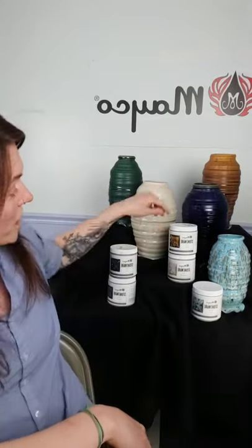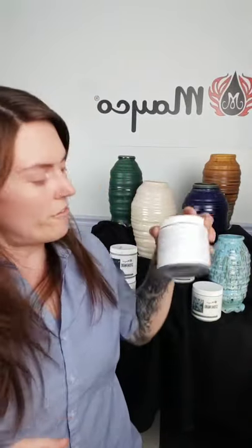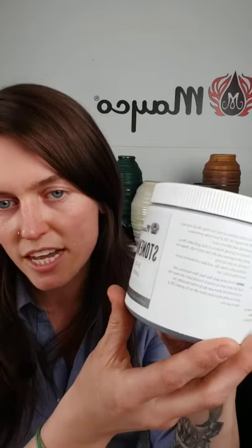Someone asked which cone 6 clay body we use for the tiles. We use Mayco's white stoneware casting slip. As for why some glazes are not recommended for dinnerware — they don't have a chemically durable finish, so long exposure to highly acidic foods will degrade the fired finish. We don't recommend putting them anywhere that will directly come into contact with food.